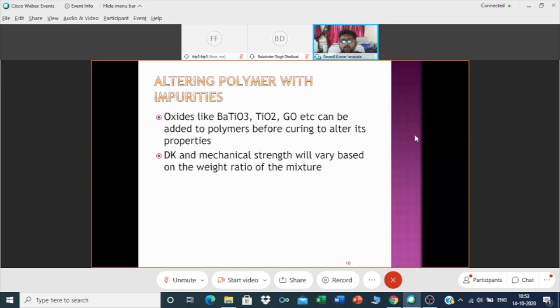Now you may want to have a high dielectric constant, you want to vary its dielectric constant, you want to vary its mechanical properties. How do you do that? By adding impurities like barium titanate, titanium oxide, zinc oxide, graphene oxide, and some ferrite based oxides also. So you can add different oxides to it, and you can alter your polymer, and your dielectric properties and mechanical properties will change based on the weight ratios you are mixing. Suppose I'm mixing 0.1 ratio of TiO2, the dielectric constant will vary differently and the mechanical strength will be different. If I'm adding 0.5 weight ratio, the dielectric constant will change again. So not only the particles that you are adding, the weight ratio will play a significant role in altering all your properties.